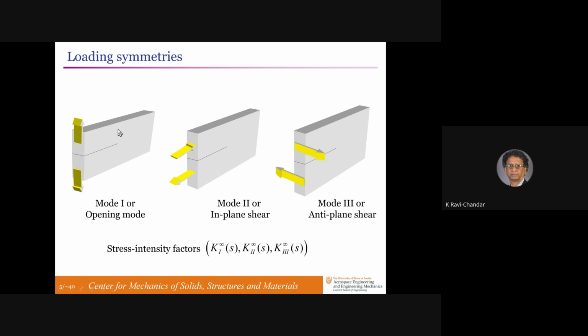Mode 1 is the one that's been considered the most. If you look in the fracture literature, probably 95+% of the papers deal with mode 1 fracture because that's the commercially important fracture mode that destroys structures and we need to be aware of. And so I won't talk about that at all because it's very well understood. There are ASTM guidelines, ANSYS guidelines on how to design with objects that have mode 1 cracks. I'll say a little bit about mode 2, but the bulk of the talk is going to be on what happens if you have mode 3 plus a little bit of mode 1 crack loading on it.